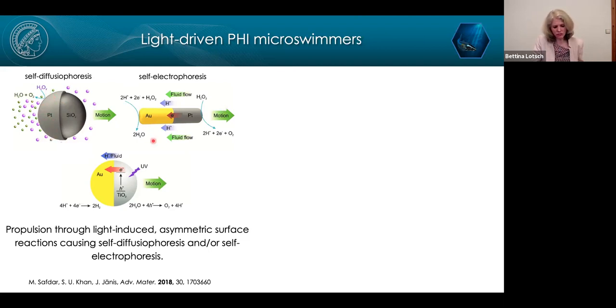Now, this asymmetric buildup of a concentration gradient around the particle can be achieved by making Janus-type particles, like shown here, where we have asymmetric surface reaction. So, for example, we have a surface reaction only on one side of the hemisphere, like, for example, hydrogen peroxide decomposition at this platinum cap. Now, self-electrophoresis is very closely related. Here we have a buildup of an internal electric field, which drags along the counter ions across the particle surface, and that then gives rise to propulsion basically in the opposite direction. And so, again, this type of motion is induced by a chemical reaction on one part of the surface, or one hemisphere of the surface.